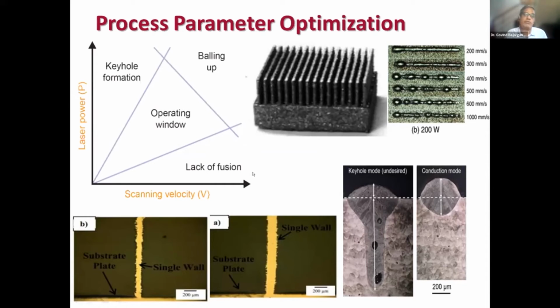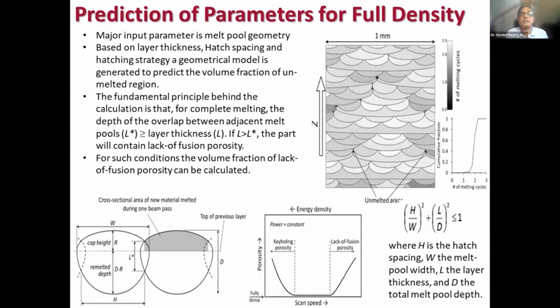So when we went ahead with building single track or single wall structures over a wide variation of power and scanning speed, this helps us in delineating the zones of lack of fusion, keyhole formation, and balling effect. With that, we can arrive at the operating window, which can give us a consistent deposit, a smooth wall with a reasonably good surface finish.